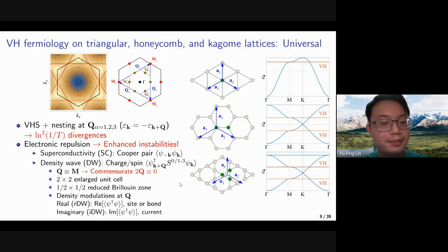So we might want to understand further what kind of density waves there could be. We can think of the density waves as the density modulations at finite momentum q. For example, if we have a charge density wave, we could have a density modulation like larger, smaller, larger along a direction. And if it is spin, then it could be up, down, up with a two lattice site periodicity. We can distinguish them further into real and imaginary channels. If it is a real density wave, the real component of psi dagger psi is the density, and it will correspond to the site or bond density modulation of charge or spin.